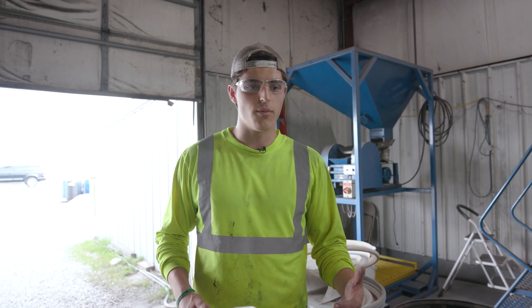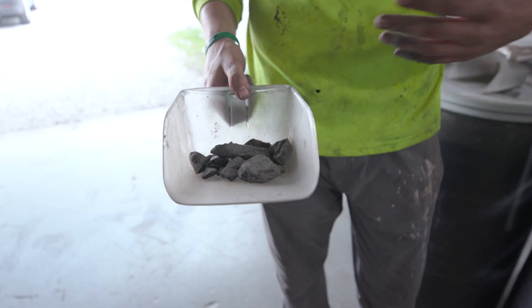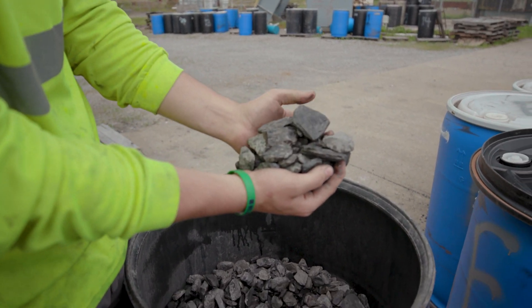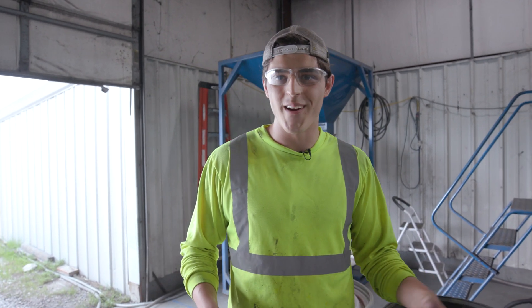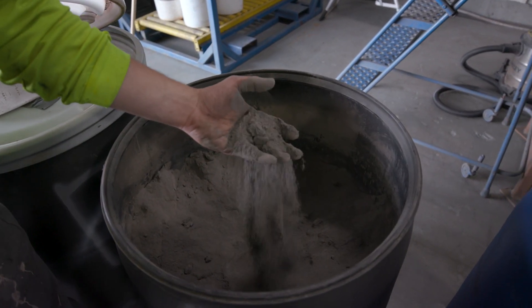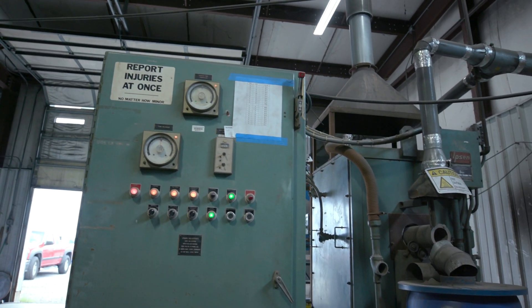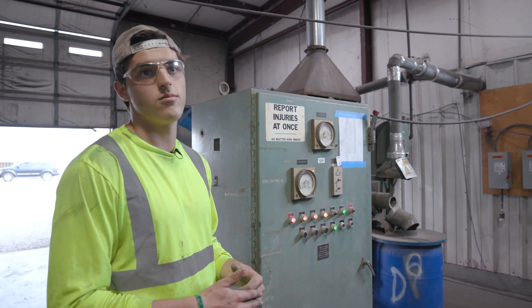This is actually the beginning of our process here at the plant. We take the waste stream from the coal processing plant — material they would originally just get rid of. We sort the middleweight particles, because that's where we find the rare earth elements. We then crush it a couple of times into a very fine dust and load it into the top of the roaster. It spins for about 45 minutes to an hour, and that tube runs at about 800 degrees Celsius. We do this step because it improves the efficiency of our leaching in the next step.